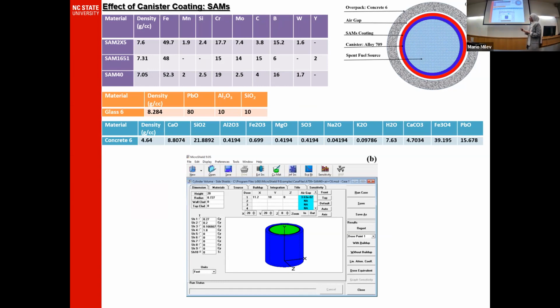So we performed the same study using Microshield, in which we used canister S709, and then changed the SAMs. We have different SAMs with different compositions, and also a glass-based coating that has a very high attenuation coefficient, so we wanted to compare it and see how its behavior is like. And then we have the final concrete, concrete 6 with this composition, a heavy concrete overpack that also exhibits very high attenuation coefficients.